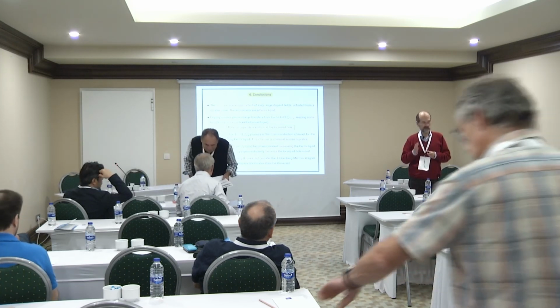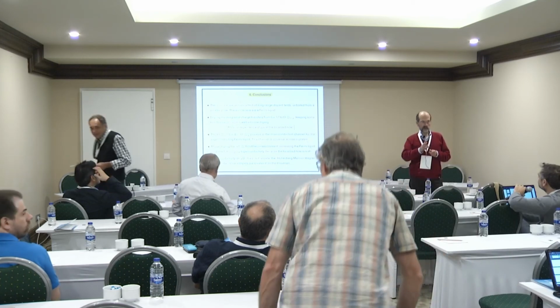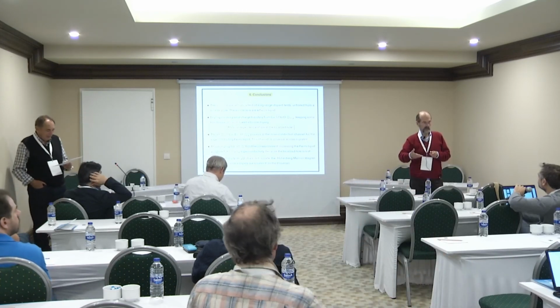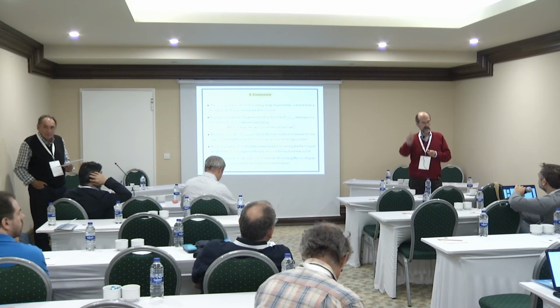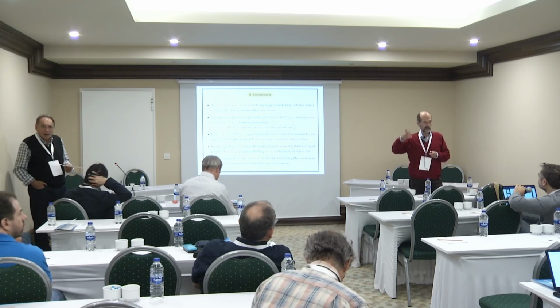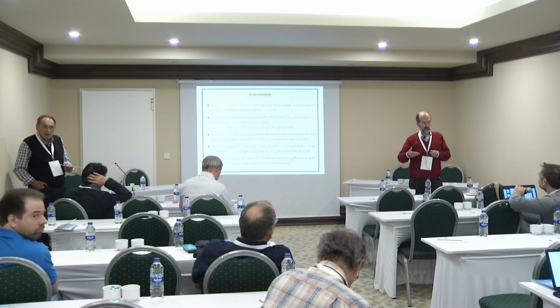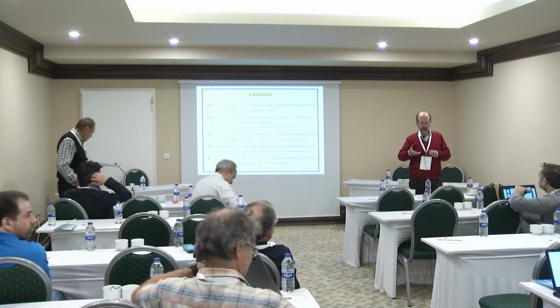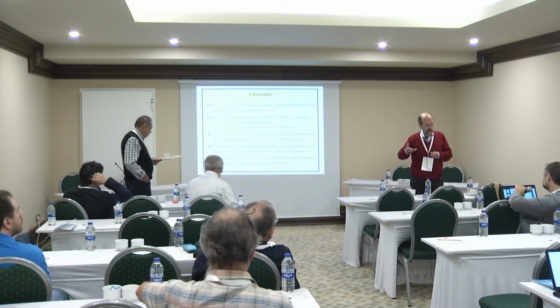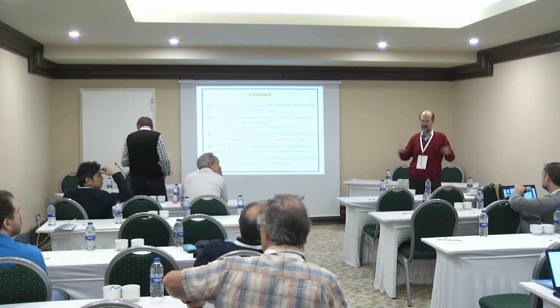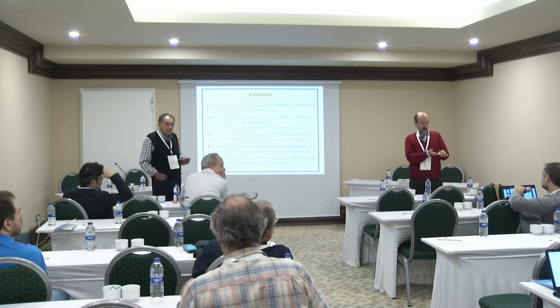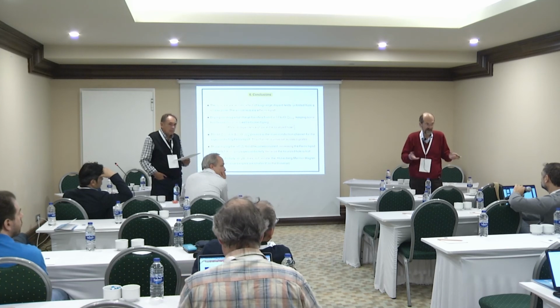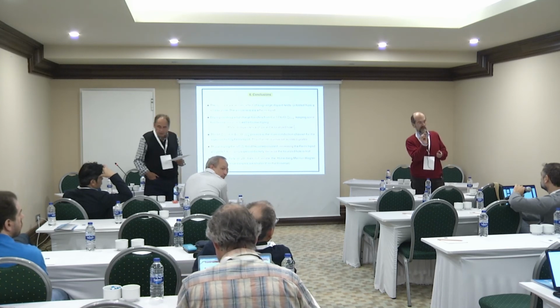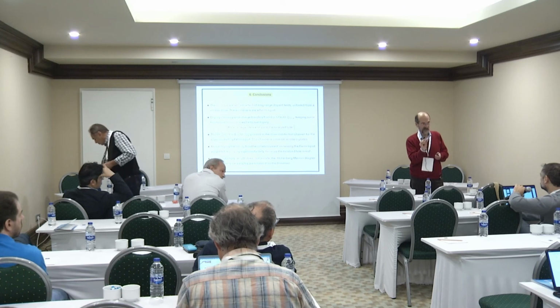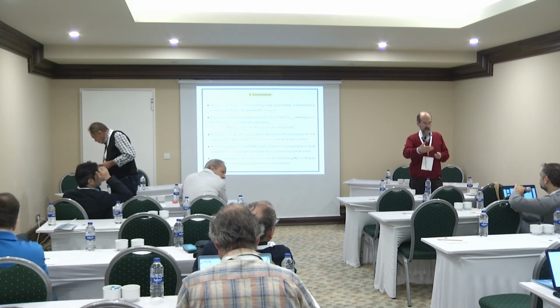Because in alloys you have the same sort of thing, where you can have the original parent material and it has these peaks, Fermi liquid peaks, surface, whatever. And then you start alloying it, and when you alloy it, very quickly translational invariance is lost. So the theoretician would say that there is no zone. But in fact what you observe is that there is a zone, and all that happens is that the peaks are no longer resolution limited. Okay? And so there is a very gradual evolution, destruction, so to say, of the zone.